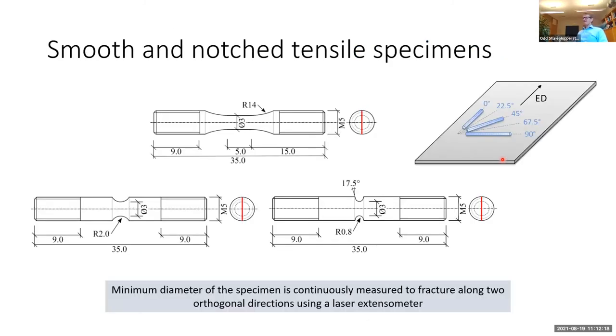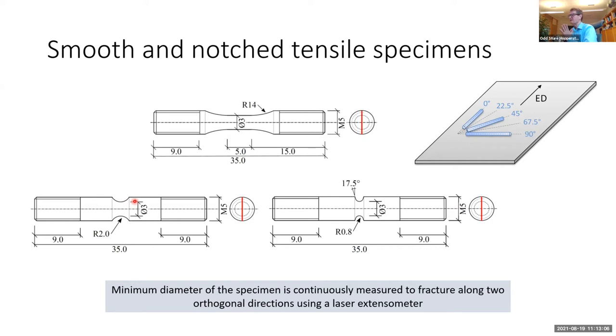For mechanical testing, we performed tensile tests on smooth and notched samples in different directions within the plane of extrusion. For smooth specimens we tested five different directions with respect to the extrusion direction; for notched specimens we tested three directions: 0°, 45°, and 90°. Notches with different radii were introduced to probe different stress states. A laser extensometer measured the minimum diameter continuously along two orthogonal directions all the way to fracture, allowing us to establish average true stress–true strain curves at the minimum cross-section.